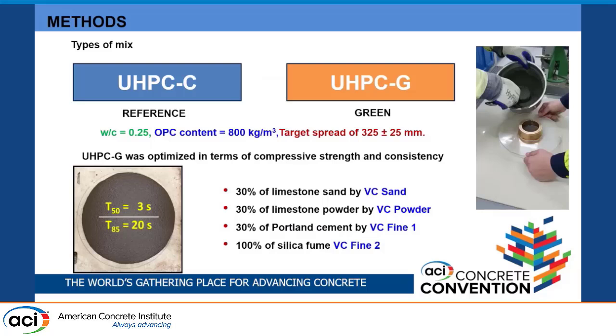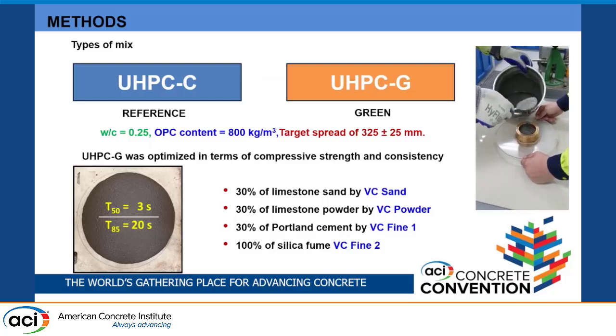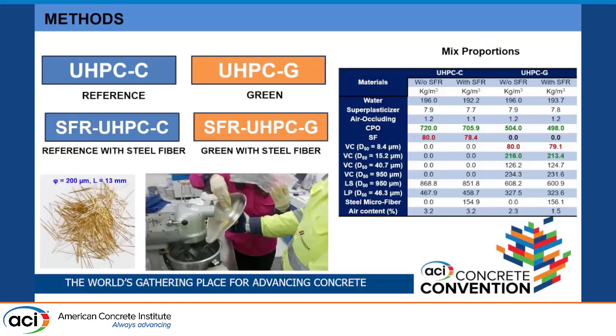And at the end, the optimal mixtures, we produce with 30% of limestone sand substituted by vitrified clay sand, 30% of limestone powder substituted by vitrified clay powder, and 30% of Portland cement by vitrified clay fine one, and we substitute 100% of silica fume. You can see how was the flowability of the concrete that we produce. It's not really a concrete, it's basically a mortar because it has only sand. Okay. And these are the proportions that we use.